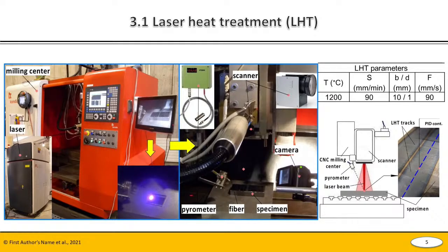Laser heat treatment of specimens was conducted using a 1 kilowatt fiber laser, high frequency scanning optics, and a milling center with numerical control. It should also be noted that during the laser heat treatment, a PID controller was implemented to ensure control of the surface temperature in the laser spot. The optimized laser parameters are presented on this slide. Next slide, please.